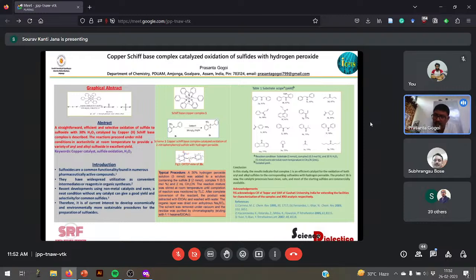Here we have prepared this range of sulfides. We prepared both aromatic sulfides as well as aliphatic sulfides. So in conclusion, the results indicate that the Schiff-base complex is an efficient catalyst for oxidation of both aryl and alkyl sulfides to the corresponding sulfoxides with hydrogen peroxide. The product given here is 3B. This product is very new. It was prepared in our lab, and it is also characterized by XRD analysis. The catalytic process is clean and safe, and most of the starting sulfides are commercially available. So this is my presentation, and thank you.